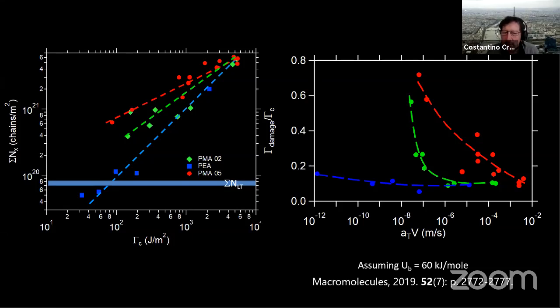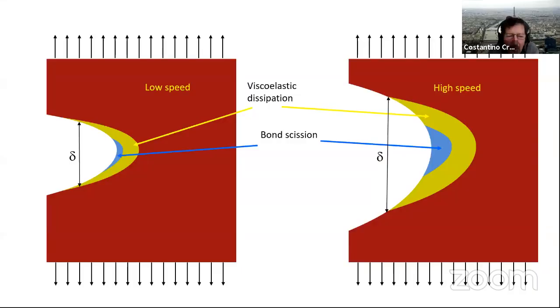So seeing all these results, what sort of picture can we have? Now I'm bringing a cartoon to try to explain our vision, but it's hypothetical. And I think it is close to some of the arguments that Bo Persson had in his review, which is: if you want to propagate your crack faster in a viscoelastic medium, you need more energy to propagate it faster. The only way to get that is to increase the opening of the crack. So you need to deform your material to increase your applied energy release rate to move the crack faster. Now this increase in G and this increase in crack opening, because here we have a strain field, also increases the stretch.